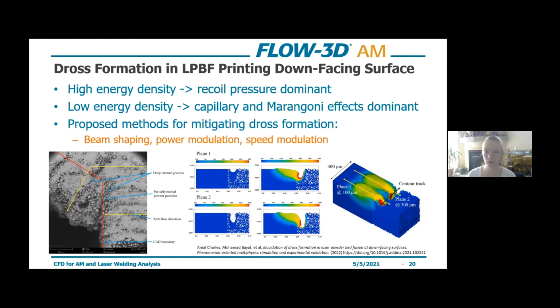So the proposed methods for mitigating this dross formation when you're going from one substrate to the next: beam shaping, which we'll look at next, power modulation, so turning down the power when you get to the powder layer, or speed modulation, so speeding up your laser, and that way you can avoid that drilling effect once you get to the overhang. And you can see from the experiments, they did a kind of quality check in terms of, do the simulations and the experiments agree in terms of the conclusions made, which there was good agreement here as well.